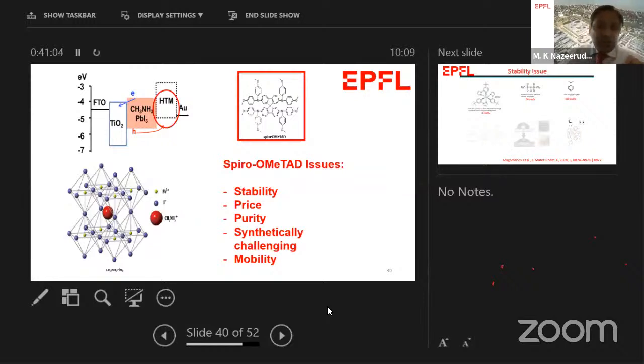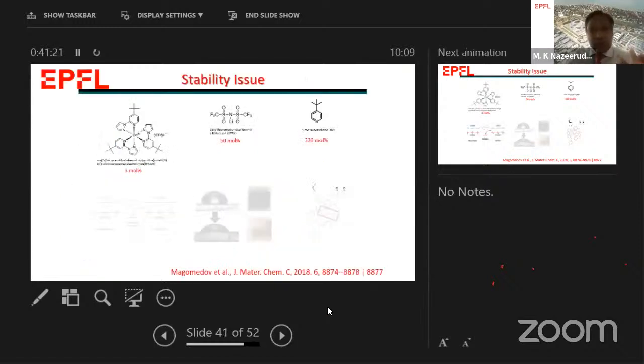On the left side, we are showing the cell configuration and energy level scheme. This particular hole transporting material has a few challenges, and the main challenge is that the mobility of this material is very low. So how can we increase the mobility? The next slide shows that many groups in the world are using this type of dopants to enhance the conductivity of this hole transporting material. Cobalt, pyrazine pyridine type ligands, tris complex, TFSI, tertiary butyl pyridine.